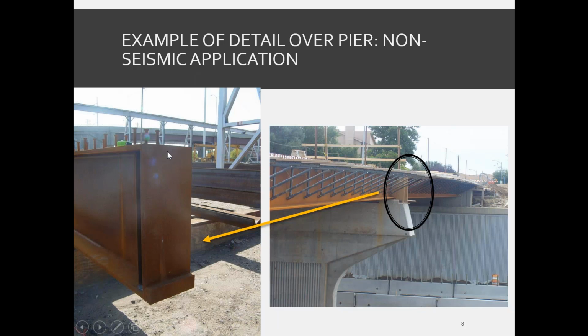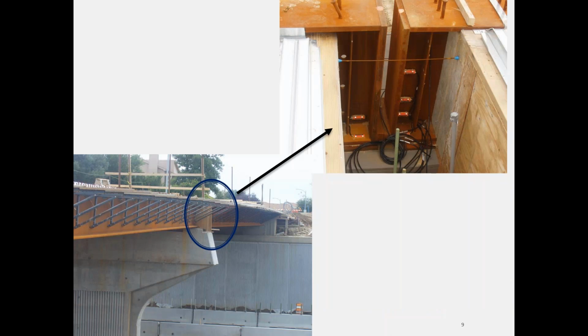One detail is the end of each girder over here, over the pier. Okay, there's an end plate, and then there's a steel block. The steel block that we have used is as wide as the width of the flange of the girder. It's about 2 inch thick, and the height is about 4 inch. Now there is a similar steel block on the other girder too. Now these steel blocks over the pier, they do not have to touch each other. Some people, they worry about the tolerances and so on. As long as you have some contact or maybe 1 inch gap, you should be fine. There is no need to have these steel blocks of one girder and the other girder to completely touch each other. Even a 1 inch gap would be just fine.